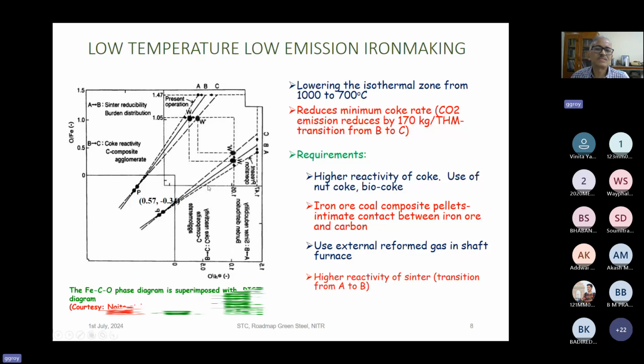That is the idea. And what you can see in the upper part is the operating line. The operating line comes from the material and heat balance, and the slope of this operating line gives you the carbon rate into the blast furnace. It has two fixed points. One is called the thermal pinch point, which comes from the heat balance. That is the fixed point for a particular heat demand, or for a particular blast furnace operating with certain materials. This Wustite equilibrium point is also fixed, because you cannot operate below that lower level of CO; you have to achieve the equilibrium point, then only the Wustite reduction will take place. And the final reduction is Wustite to iron. So you cannot cross the Wustite line. These two points fix the minimum carbon rate into the blast furnace.